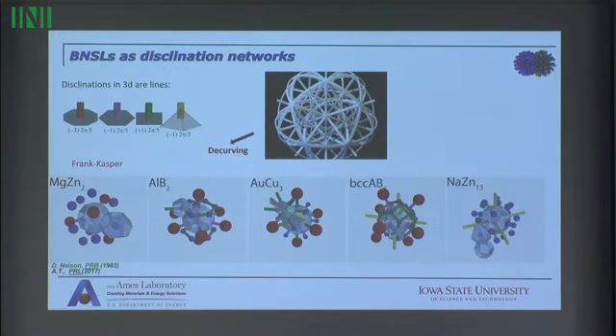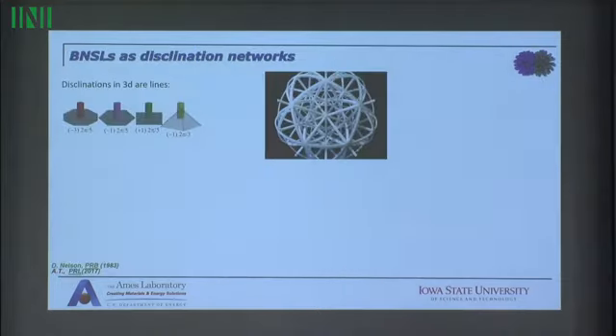In other words, all the superlattices that have been found experimentally, and that includes also DNA, which I haven't talked about, are also not Frank-Kasper phases, but what we call quasi-Frank-Kasper phases, in the sense that they are combinations of these disclinations, of these types. So here you have, for example, aluminum boron 2, which I mentioned before, sodium zinc 13, and so on. Sodium zinc 13 is my favorite because it's actually made of -2 pi/3 disclinations.